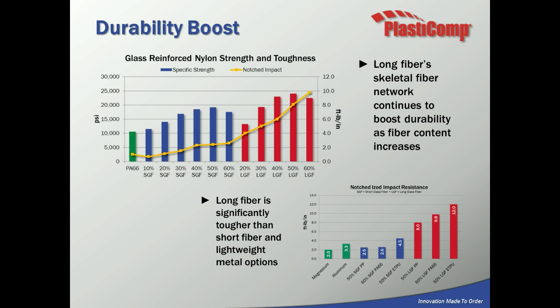And the graph on the top here is just comparing short glass nylon to long glass nylon at different percentages. And where I want you to focus your time is over to the right, where we're looking at long glass materials. You can see over the right that they have the highest impact resistance, or notched Izod impact resistance, and also the highest strength. If we look into the bottom right-hand corner, we're comparing some of our long glass materials to metals, lightweighting metals, specifically magnesium and aluminum, and you can see our impact resistance is higher than those metal materials.